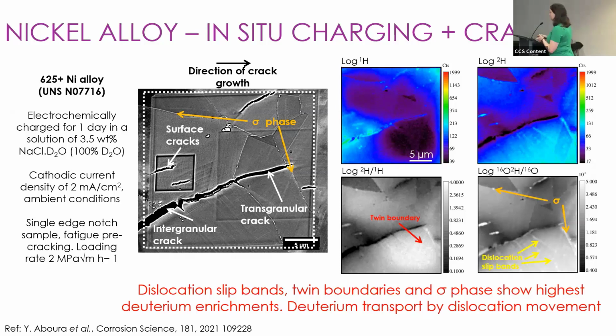So again, the projector's not the best, but hopefully you can see we've now got deuterium localizing to dislocation slip bands. We also get deuterium localizing to the sigma phase, and you can sometimes see deuterium localizing to this twin boundary here. So what we've now got is mobile dislocations that are transporting deuterium with them as they are moving through the metal, and they're picking up the deuterium, and you're seeing this accumulation of deuterium at these particular regions.